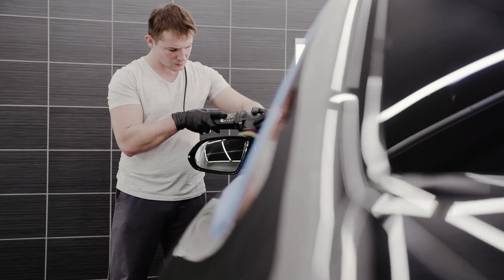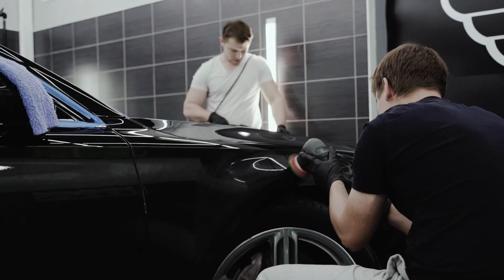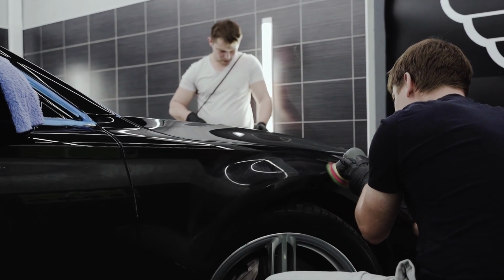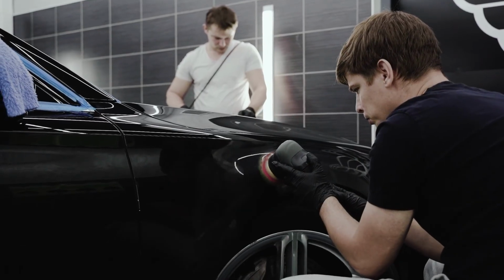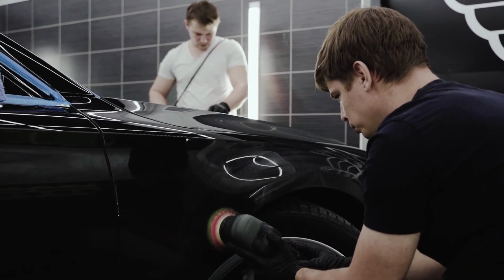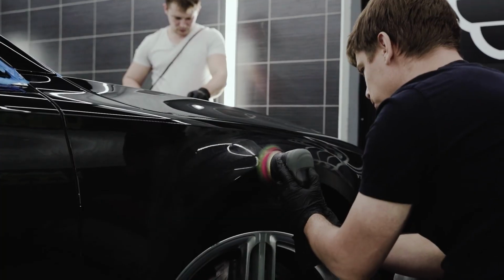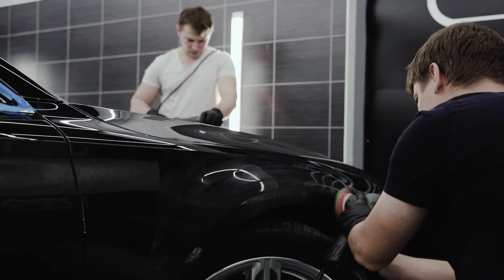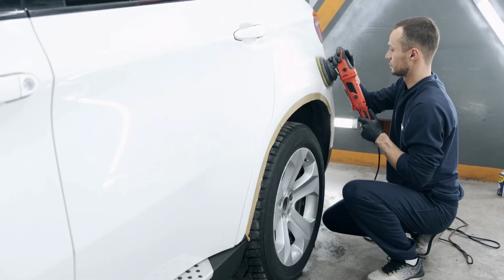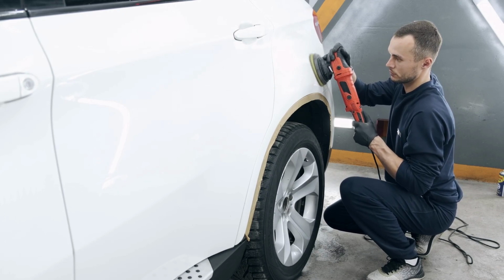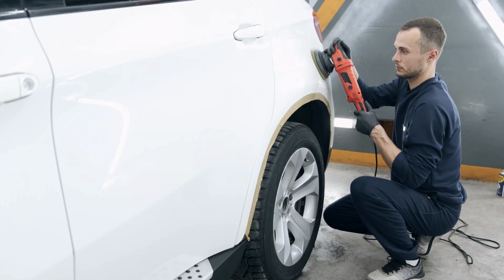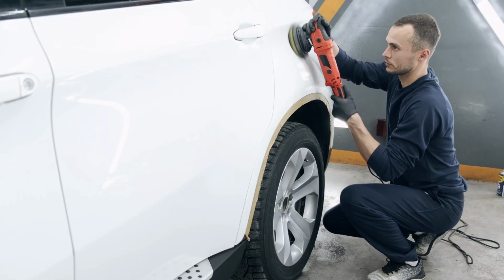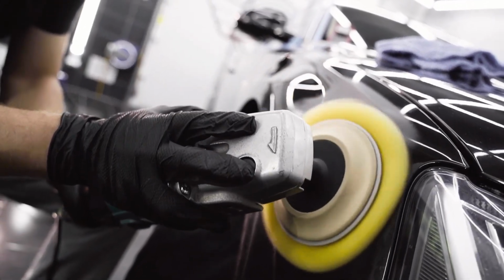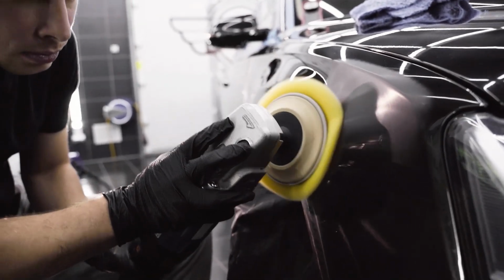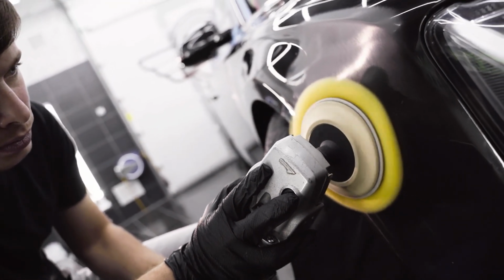The key here is to avoid the holograms, those circular marks that are seen under the light of the sun. To achieve it, a dual action, orbital polisher must be utilized that imitates the movement of the hand but at a constant speed. The aluminum oxide is preferred over the silicone because it generates less heat, reducing the risk of burning the polycarbonate. A good technician knows that the polishing does not end when the headlight shines, but when, upon cleaning with isopropyl alcohol, the surface continues being perfect. If the brilliance goes away with the alcohol, it means that the polish had fillers, oils that cover the scratches, and the work is badly done.